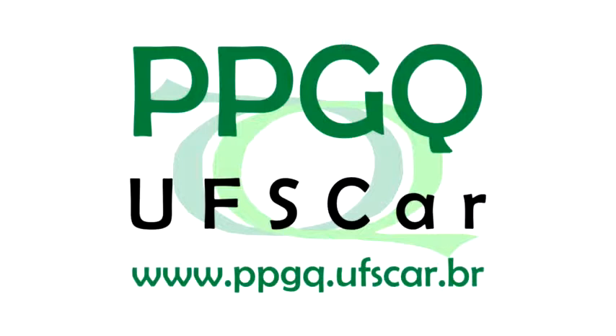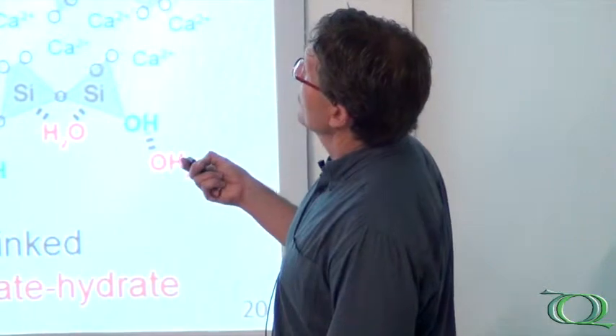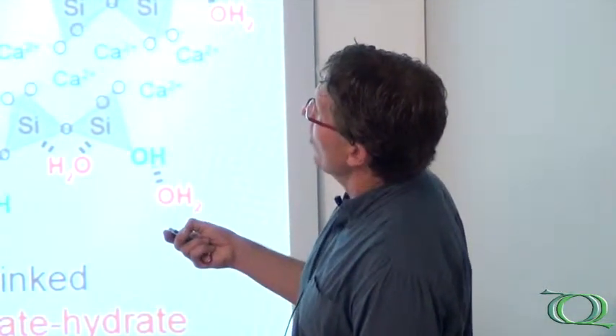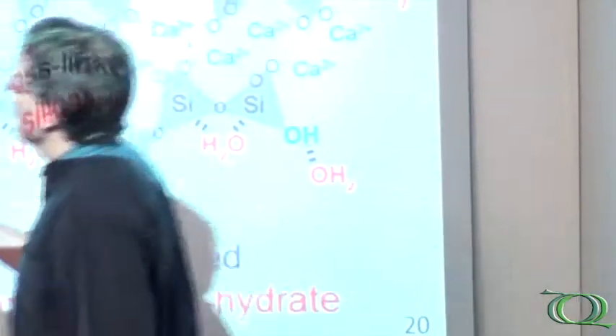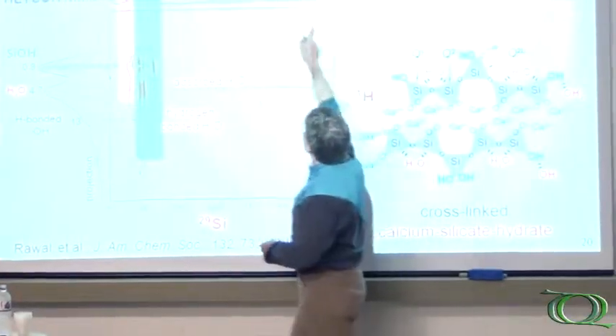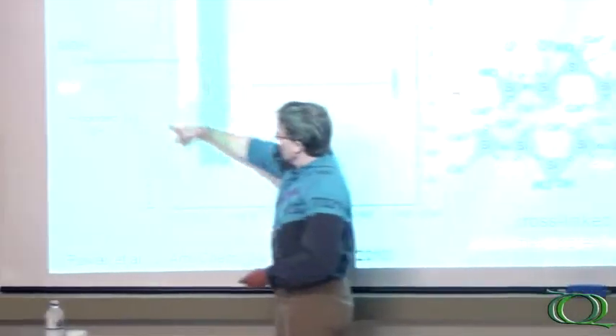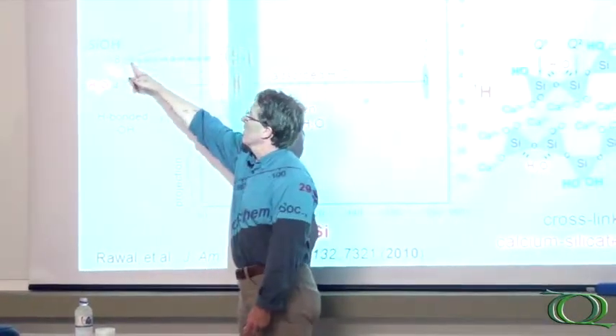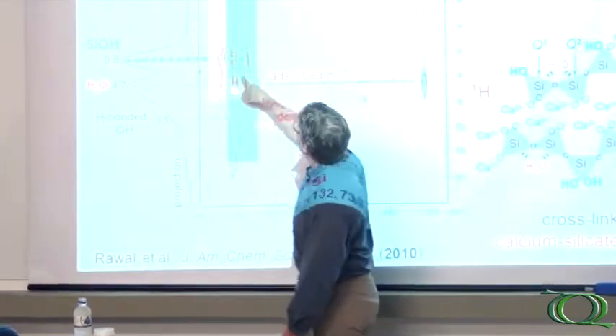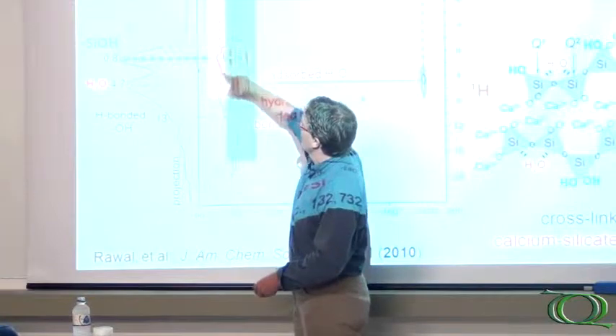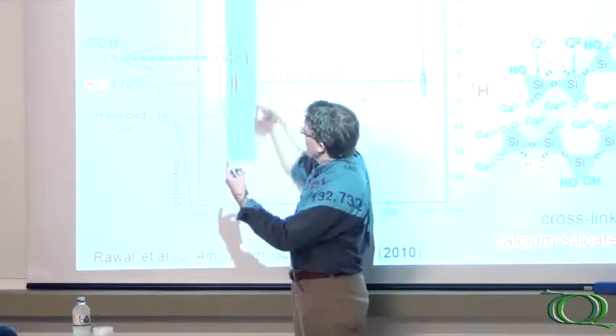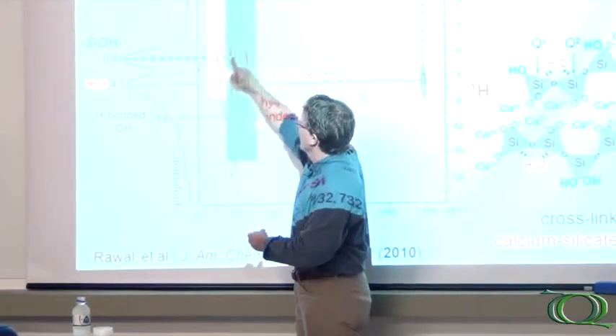And to give you an idea, so you form these type of structures, and this is at 95 degrees Celsius at 24 hours, pH 13, this is even higher, hydrated white portland cement. Now what you do is you have, you start off with these calcium silicates, they're so-called Q0 species. The Q1 are evidence of the hydration, and you can see this because after, you now have the same types of measurements, you have the silicon spectrum here, and you have the proton spectrum. The proton spectrum here is simpler, you have silicon silanols, and water, and you see the Q0s, these are anhydrous, very low signal from these, but the hydrated species form crosslinks.